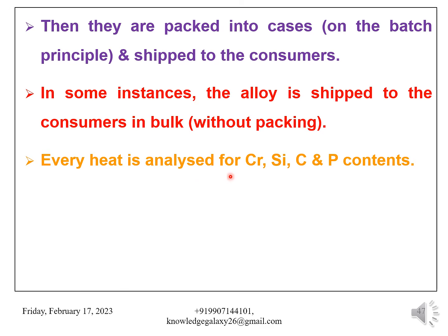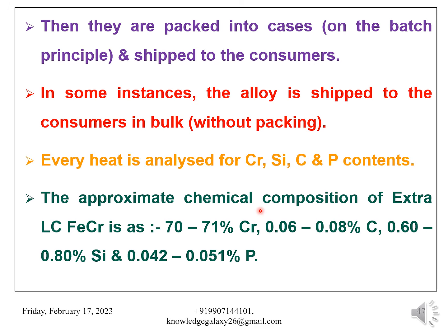Every heat is analyzed for chromium, silicon, carbon and phosphorus contents. The approximate chemical composition of extra low carbon ferrochrome is 70 to 71% chromium, 0.06 to 0.08% carbon, 0.60 to 0.80% silicon and 0.042 to 0.051% phosphorus. This is a typical example of analysis of extra low carbon ferrochrome.